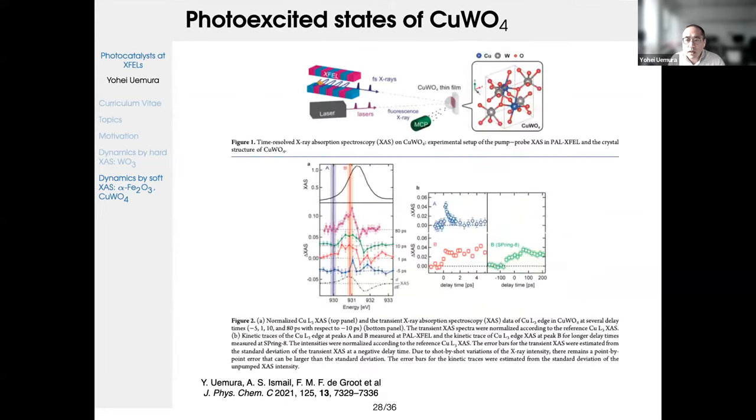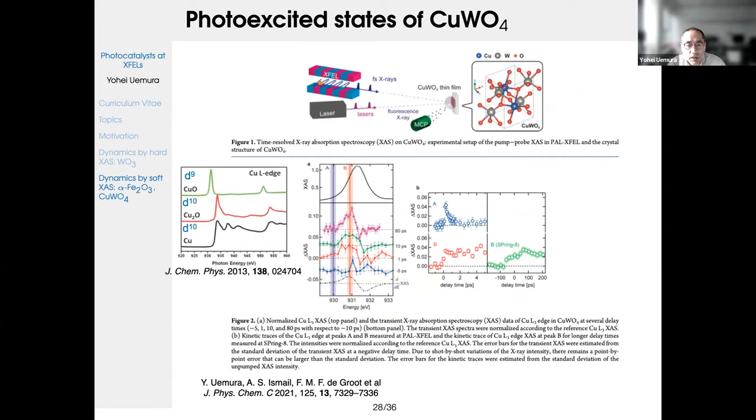So we measured the copper tungstate at the XFEL. We got good transient signals of the copper L3-edge. We found that, comparing the first derivative of the copper L3-edge spectrum, the copper L3-edge spectrum shifts to the lower energy side.